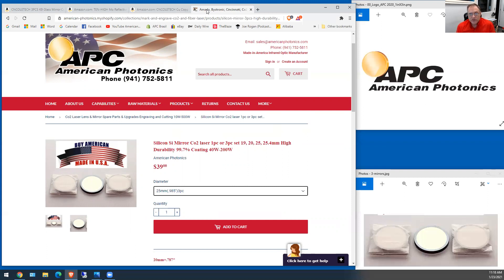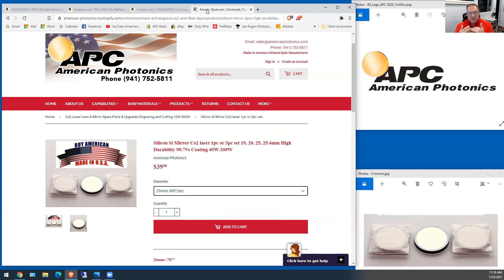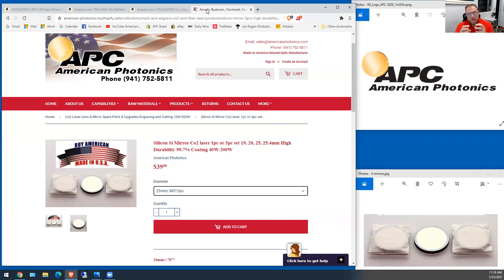I'm using an old design. Now my mirrors are silver looking where a lot of them are gold looking. The only difference there is in that layering I use zinc sulfide instead of zinc selenide. So it just gives it, where if I use zinc selenide as the outside layer which is that orange material it gives it a gold look. Zinc sulfide is very, very almost identically chemically the same as zinc selenide but it's clear in color.